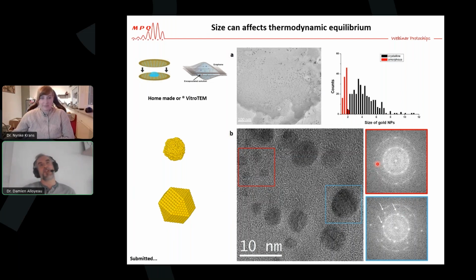Yes, that's something we took into account. What we did to prove these points, we have a very good resolution on those images, about one angstrom resolution here. With this type of resolution, we simulated the structure of crystalline nanoparticles, 1,000 images with various orientations. It turns out that only 4% of the images show a crystalline nanoparticle that would look amorphous, meaning that the angular range along which crystalline nanoparticles appear amorphous with this type of resolution is extremely narrow. So it's very unlikely that each nanoparticle that we have observed turns out to be in an out of Bragg condition orientation each time it goes below 2 nanometers.